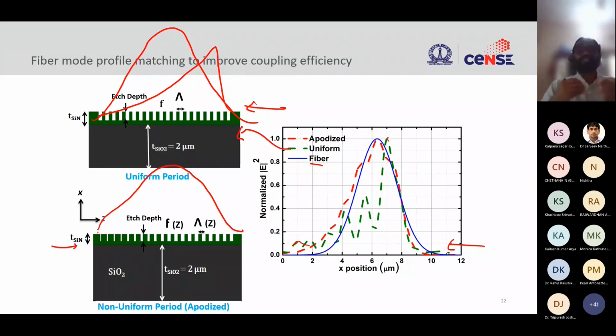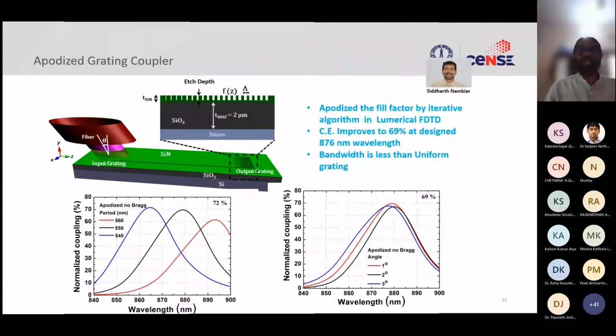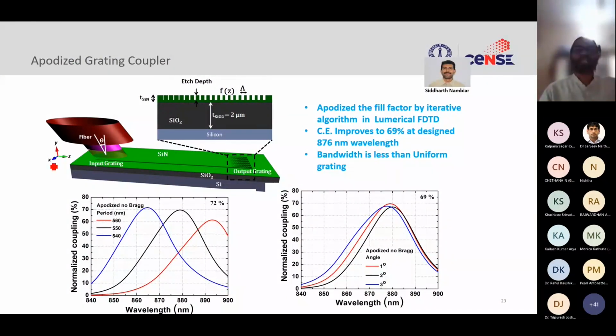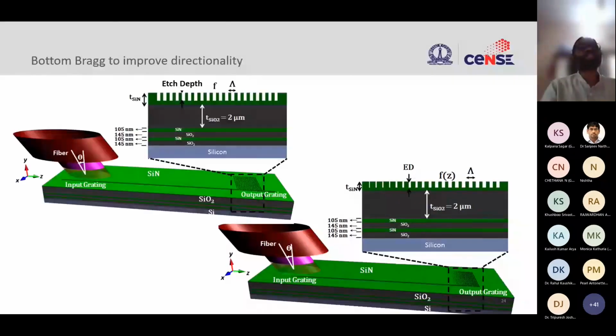Now the question is, okay, it fits into the shape, but how does this fitting translate to efficiency, right? And this is what it results in. So from 46-47%, we are now in the 70% range. So we can improve this efficiency from 45-46% to 70% by profiling the outgoing field. Okay, but then still you can say this is not 90, this is not 80, there is still something left, right? And we can also look at that. So how do we even improve that, right?